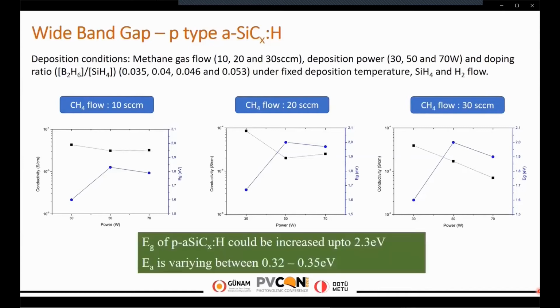In our optimization set, we were able to increase the band gap value of the p-type amorphous silicon carbide layer up to 2.3 electron volt. And for these deposition conditions, the activation energy is varying between 0.32 and 0.35 electron volt. In this set, we picked two different deposition conditions in terms of their conductivity and band gap value. Then we insert them into the silicon heterojunction solar cell structure.